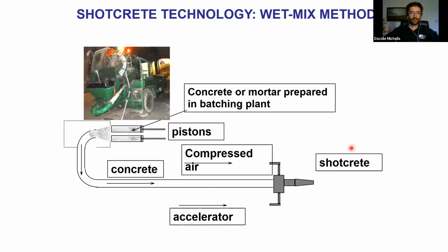On the other hand, this is again a scheme of how the wet process works. The wet mix is poured inside the hopper, and the pistons push the concrete inside the pipe to the nozzle. Only here, compressed air is added at the nozzle along with the accelerator. The accelerator is dosed according to the different situations we may face, depending on whether it is overhead or on the sides, and we get the final shotcrete that is sprayed against the substrate.